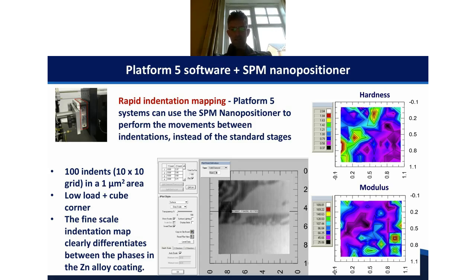So here's something that Adrian did, looking at a zinc alloy coating. So this is a 10 by 10 micron topographic image of the surface. Again, this image is not there to create the prettiest image in the world. This area is used to create a topographic map that can be used to precisely position the indent in specific phases. In this case, what Adrian's then done is he's zoomed in there and said, actually, what I want is a 10 by 10 matrix of indentations within that 1 by 1 square micron area.